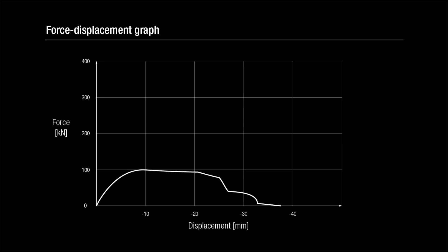The ultimate compressive strength perpendicular to grain is difficult to measure precisely, given the continuously rising stress-strain behavior of cellular wood. Under severe loading, the deformations will continue to accumulate until the volume is compressed to about one-third of its original.